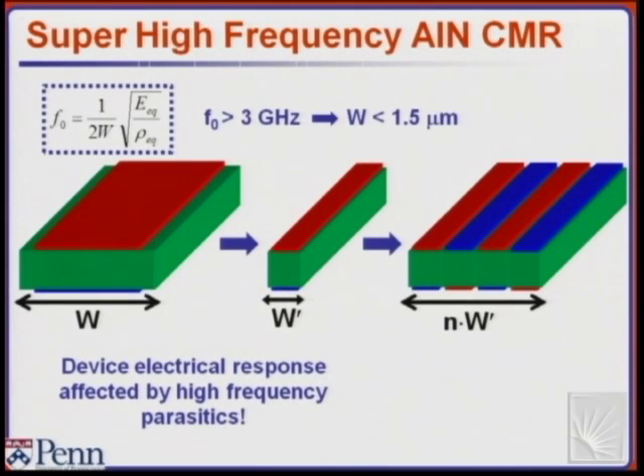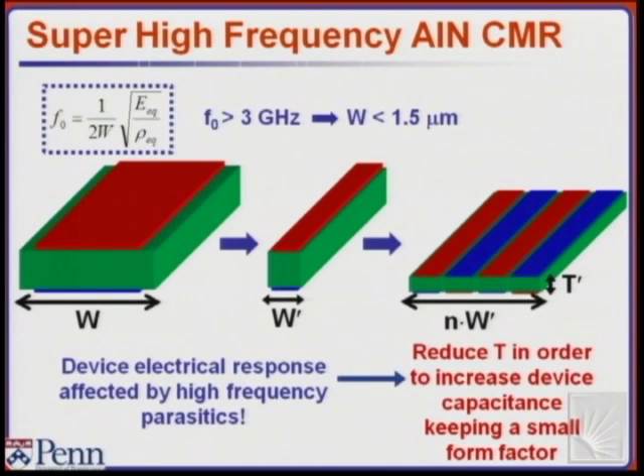But there's still a problem above 3 gigahertz. The parasitic capacitance of your substrate is starting to become comparable to the capacitance of your device. So any energy you're putting into your device actually gets split between the device and the substrate. So it's a little bit of a problem. So we try to preserve the same area and we don't want to just make the device gigantic, which we could do, but it's probably sort of a brute force approach. It's probably better to try to thin the device down. So you increase the capacitance of the device and you make it bigger than the capacitance of your substrate by making it thinner.